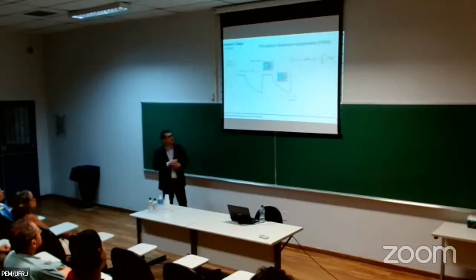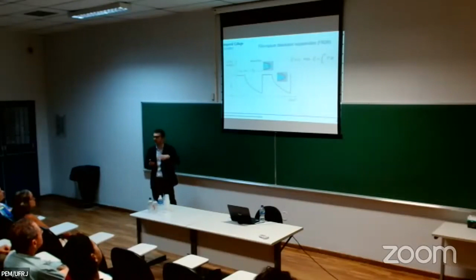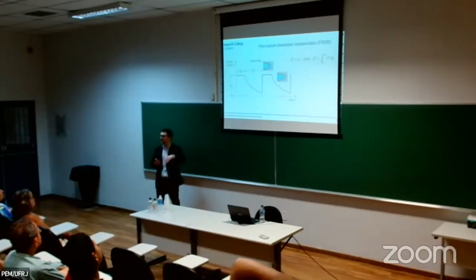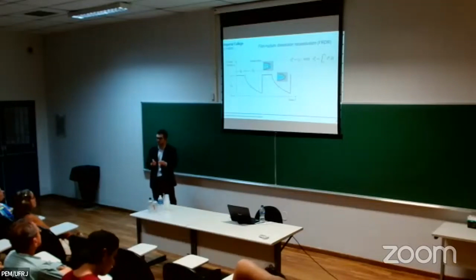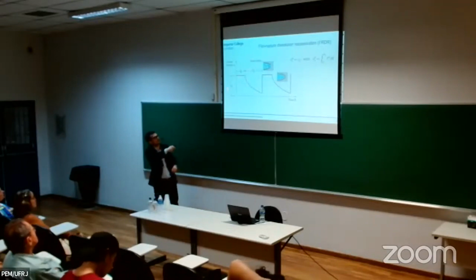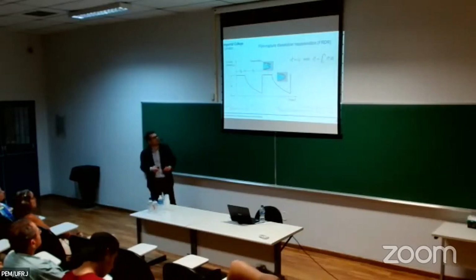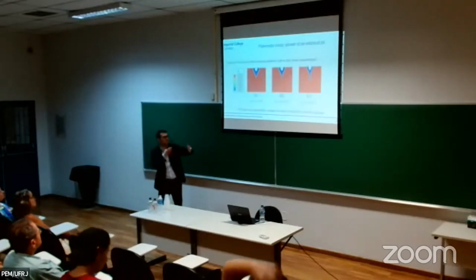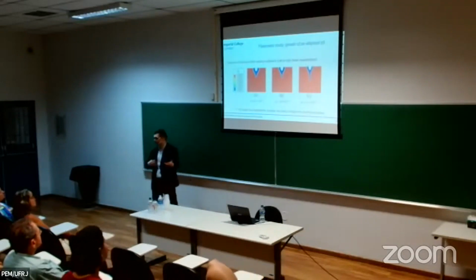And the last thing that I want to say is that we have also extended this to account for film rupture and repassivation kinetics. So normally, for example, in stainless steel, you will create a film that will protect the metal from corroding, but we get localized corrosion and pitting and stress corrosion cracking because that film ruptures eventually. So effectively, your corrosion process is a competition between the strain rates and the repassivation rates. So we can capture that. We can capture how the film eventually ruptures and then repassivates, again by defining suitably the mobility condition. And you can see here this example of the different environments. We have faster or slower repassivation, and we see the trends with respect to different experiments.